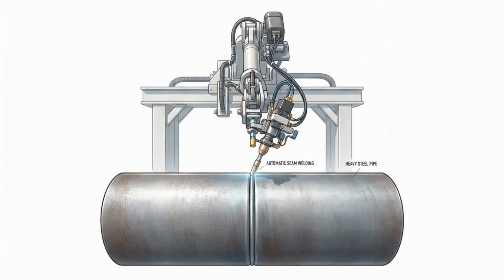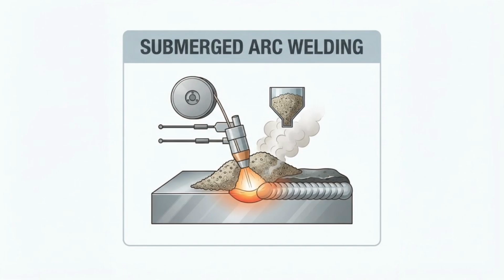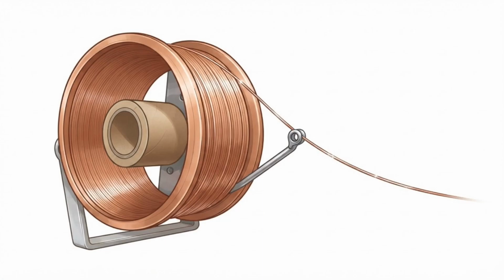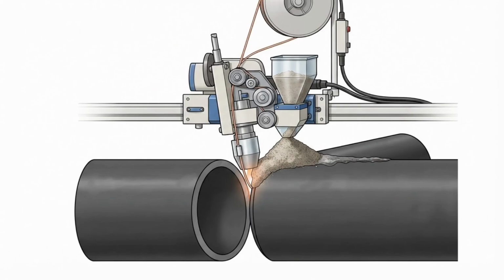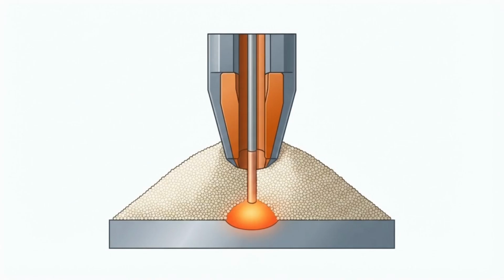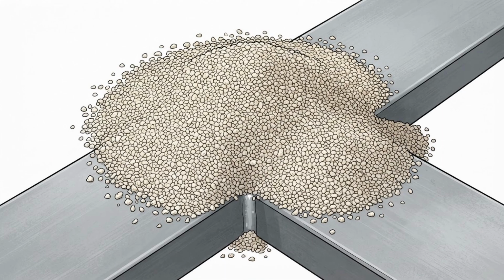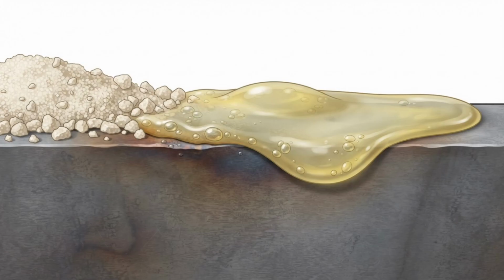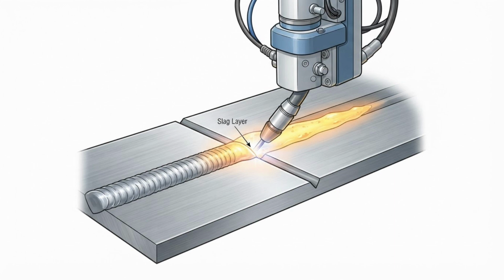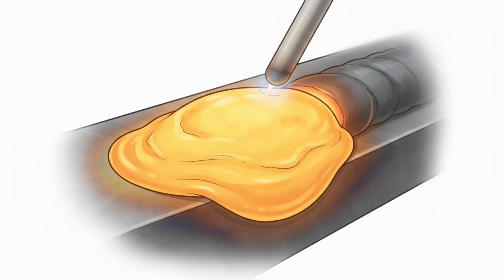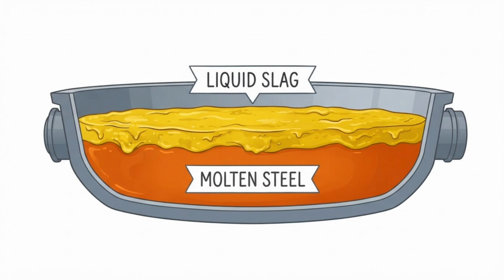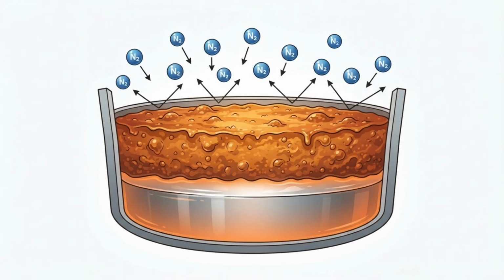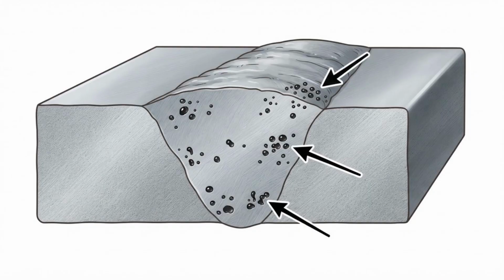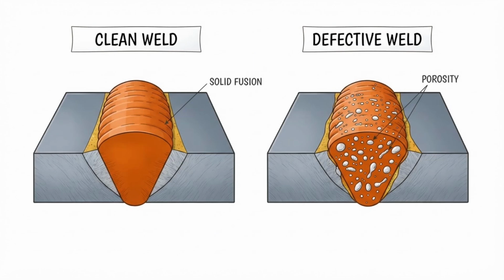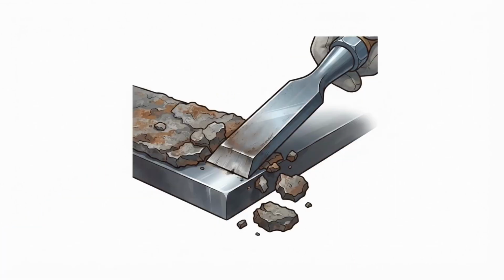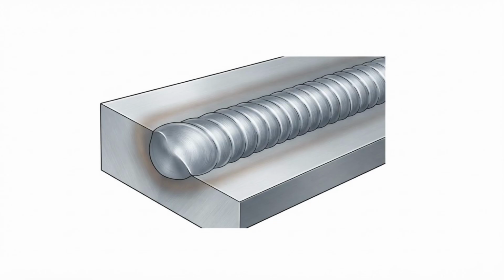This is done using a highly efficient automated process called submerged arc welding. A continuous spool of bare steel wire is fed into the seam, but the actual welding arc is entirely buried beneath a thick layer of granular flux powder. As the electric arc melts the steel, the flux melts alongside it, creating a liquid slag that floats to the top of the molten weld pool. This slag acts as an impenetrable barrier, protecting the liquid steel from oxygen and nitrogen in the atmosphere, which would otherwise cause brittle microscopic bubbles in the weld. As the metal cools, the solid slag simply peels away, revealing a perfectly smooth, defect-free joint.